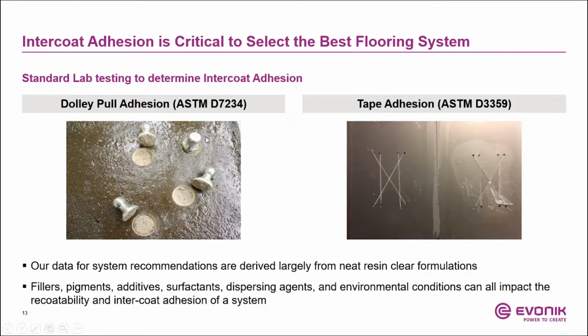As I mentioned in the previous slides, all those coating recommendations are shown to have good adhesion. However, as you know, formulators will usually add additional ingredients to the formulation: fillers, pigments, additives, surfactants, dispersing agents, and other things, and even environmental conditions can all have impact on intercoat adhesion and recoatability. So we always recommend our customers to test the intercoat adhesion of the final formulation. You do not want to get to the job and then apply it and then see failures.